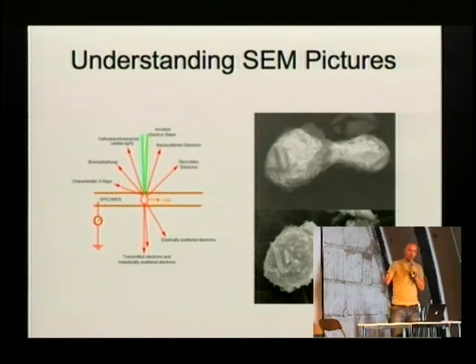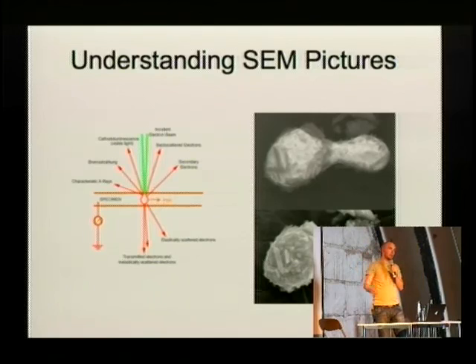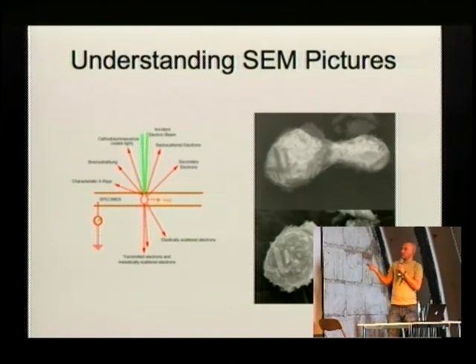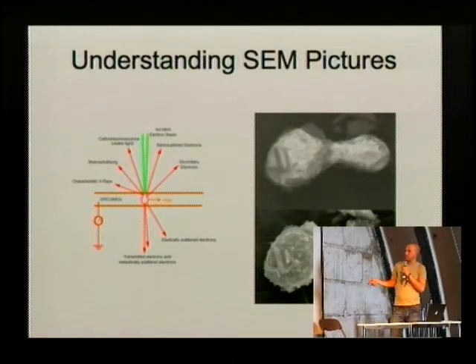Backscattered electrons are electrons coming from the beam that get reflected by the material. If you look at those, you get a nice map of the elemental composition of the specimen you're looking at. If you look at the secondary electrons, which are created by the incident beam kicking out other electrons, then you get an image with more surface information.